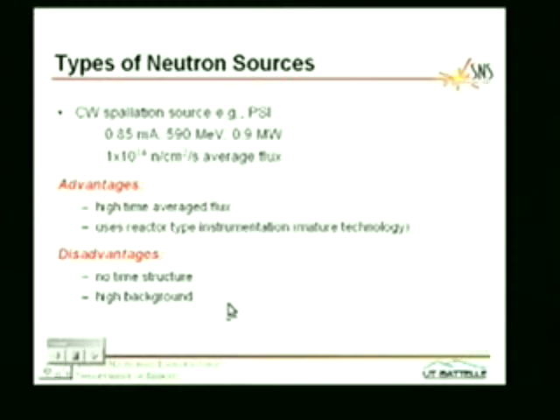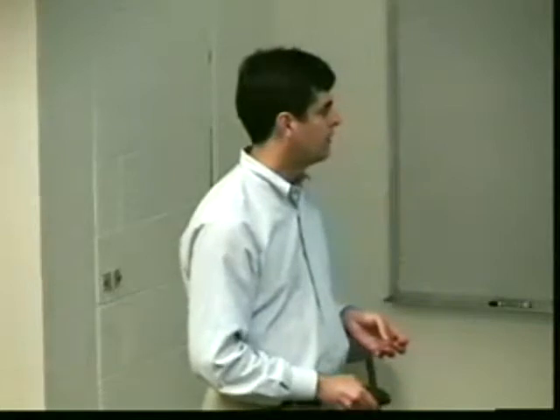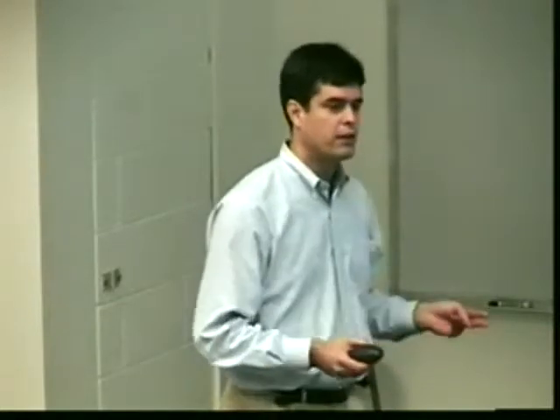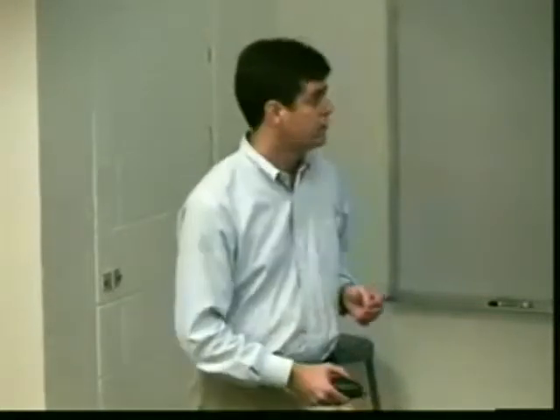There was a fear that you would have a high background, because with a pulse source, the way it works is you make the neutrons with the proton beam, and then you wait for a bit and you begin counting them as they fly down your instrument. So you're doing all your counting when the beam is off, which is an advantage in terms of signal to noise. You can't do that with a continuous source. So there was a fear that, with all kinds of crap produced in the spallation reaction, the signal to noise would be a problem. They worked really hard on the shielding and got it right, so it hasn't been an issue in this case.